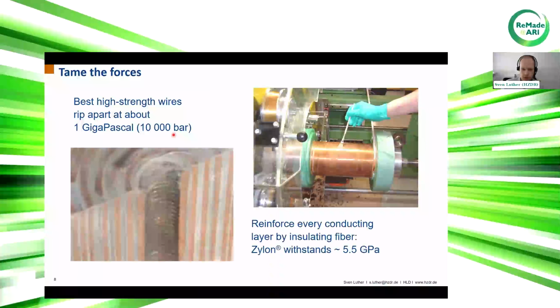And in our workshop, we reinforce them with an insulating fiber called Zylon. And Zylon withstands a pressure of up to 5.5 gigapascal. So you can see here from our workshop how these coils are wound. You have these copper alloy cables or layers, and in between every layer, we put this Zylon, which you can see here. If we cut such a coil open, you have these layers of copper alloy wires, and in between we have these Zylon insulating layers to hold our coil together.